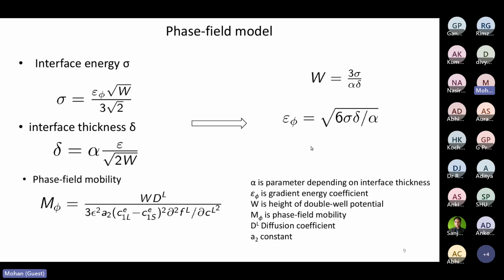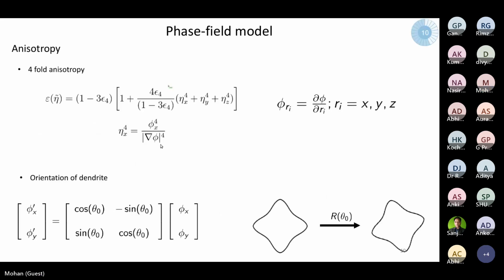So if you start writing all the parameters, you will end up with one free variable, which is nothing but the interface thickness, based upon which you will choose the discretization values for a given interface width. That is the beauty of the phase field model, which is controlled only by your interface width. The rest of the parameters are the material parameters.